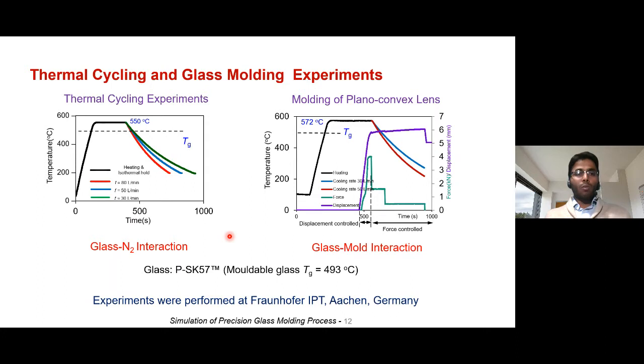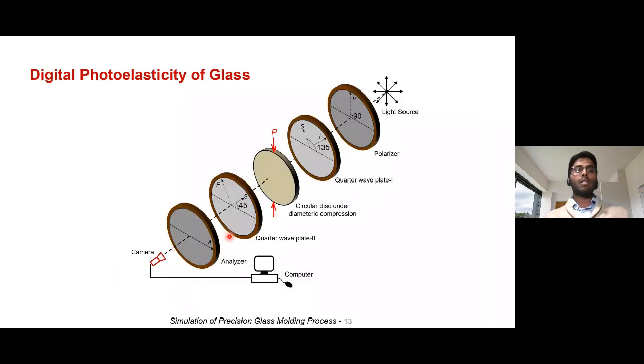Now once we had the fabricated samples, we planned to measure the residual birefringence, or in other words, residual stresses in the lens. For this, we use a circular polariscope arrangement to quantify the residual stress. Before I show you what happens with the glass, conventionally these experiments are done on polymer specimens which exhibit photoelastic effects. These are epoxy specimens. When you apply external load on it, you would be able to see photoelastic fringes something like this.